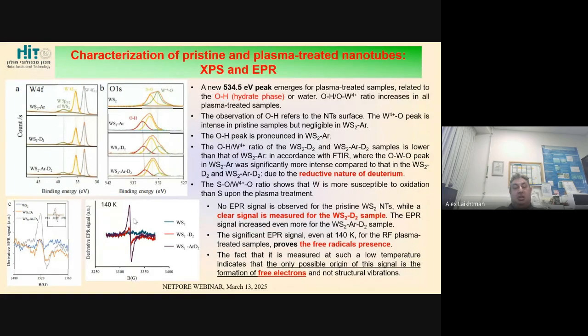And even at a low temperature of 140 K, we obtained the signal, which proved that we have free radical presence and not something else, and not some kind of vibration excitation. So the fact that it's measured at such a low temperature for sure confirms that we still have free radicals and defects even some time after performing the plasma process, because to do the EPR we had to take the samples from the plasma and then move them to the EPR machine for the measurements.